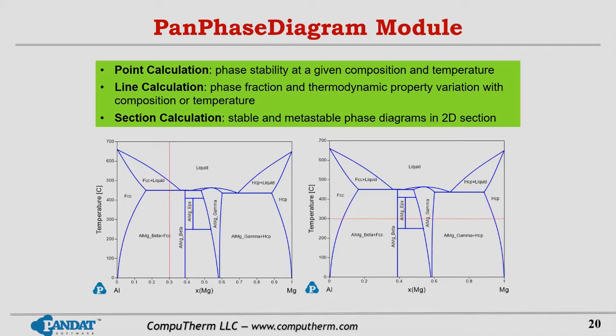However, if you want to know some details, like if you have an alloy and you want to know how it goes through phase transformation and phase fraction change when temperature changes, then you can do a line calculation, like the one shown in the figure. You have a fixed composition and do a line calculation at different temperatures. Certainly, you can also fix the temperature and vary the composition. And I want to mention that this line calculation is not limited to binaries, you can do the simulation in a multi-component system.